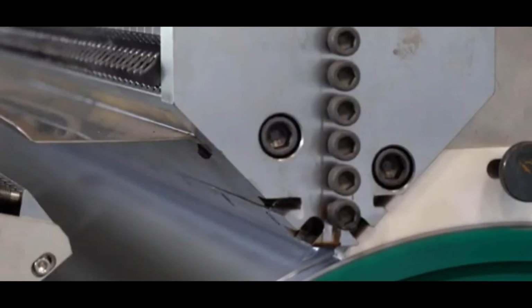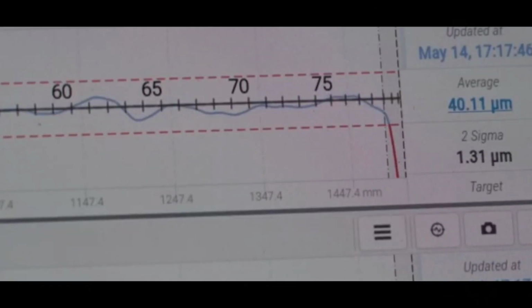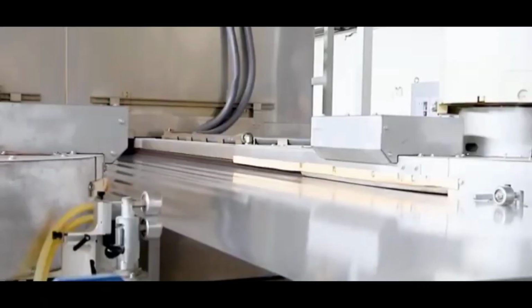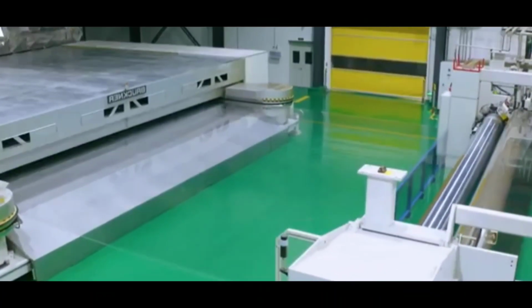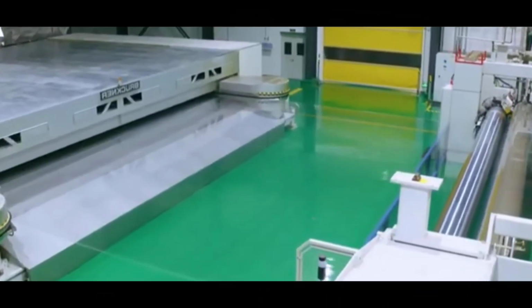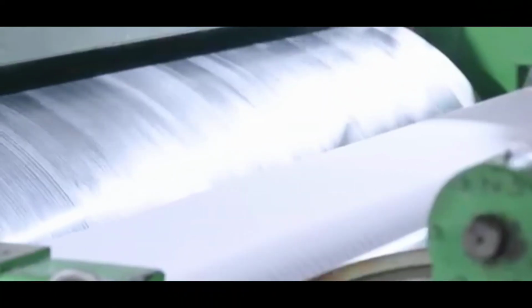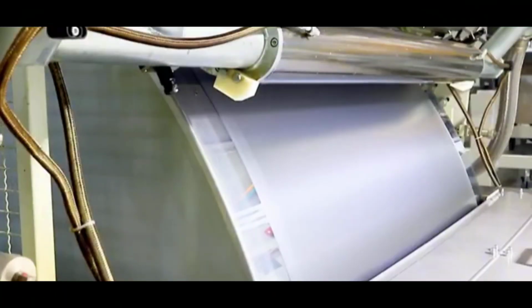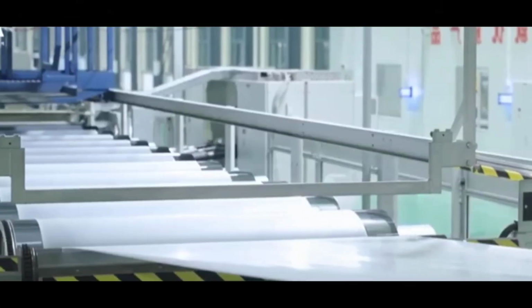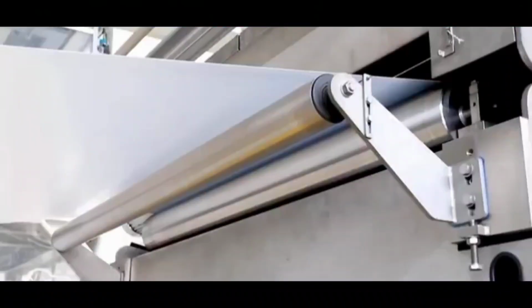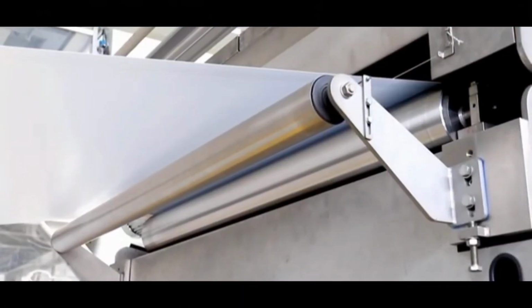This technology allows for more precise control of film thickness and flatness, thanks to the immediate cooling that occurs as the polymer comes into contact with a metal roll cooled by circulating water at around 60 to 70 degrees Fahrenheit. Rapid cooling freezes the polymer's crystalline structure, creating a surface that is smoother, glossier, and optically clearer than blown film.